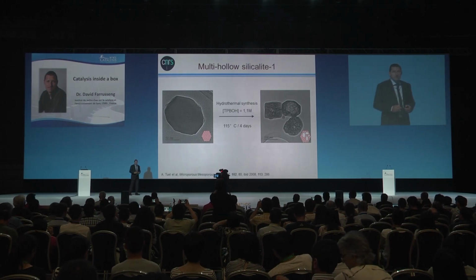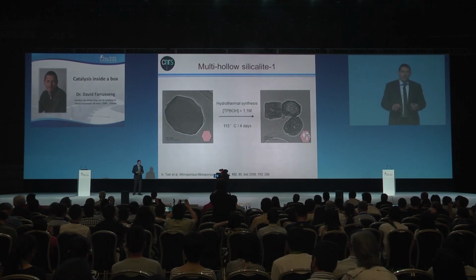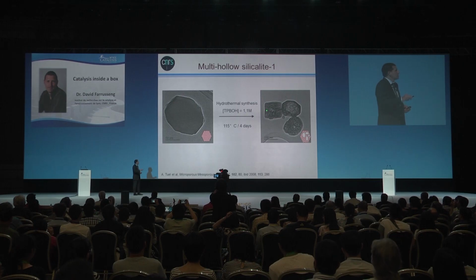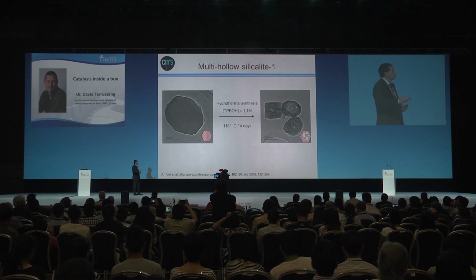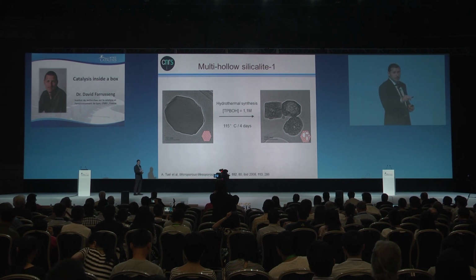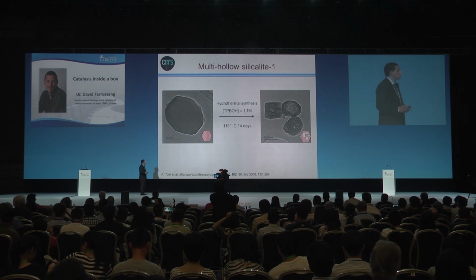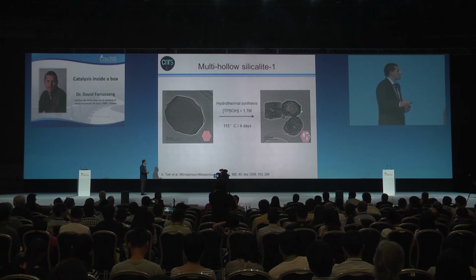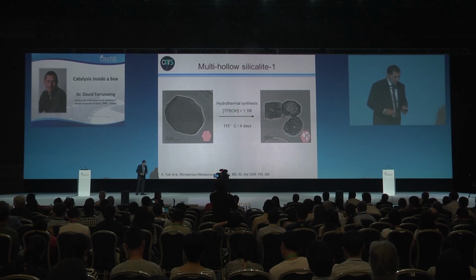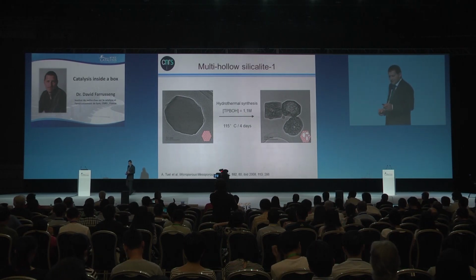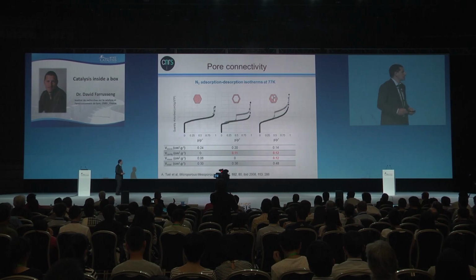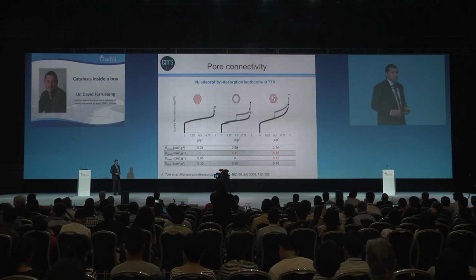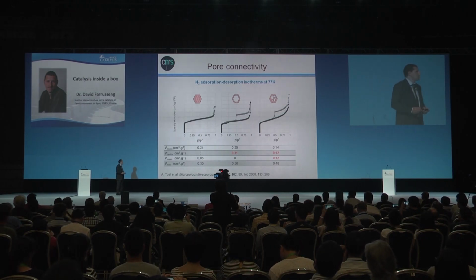At this point, it's very important to know whether this cavity, either the big one or the smaller one, has direct access to the exterior of the crystals, or if they are separated by the thin membrane here, like around. And we can learn that by looking at the adsorption isotherms of nitrogen at 77 K.